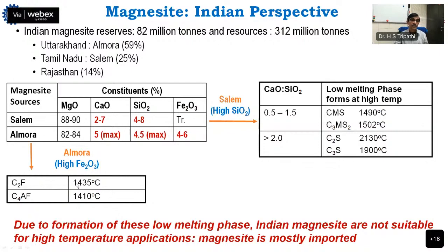But in the Almora region, it contains iron oxide. You see the iron oxide and silica. So with the lime, it forms dicalcium ferrite, tetracalcium aluminoferrite. They have a low melting point. So due to the formation of these low melting phases, the Indian magnesites are not suitable for high temperature application. And magnesite is mostly imported.